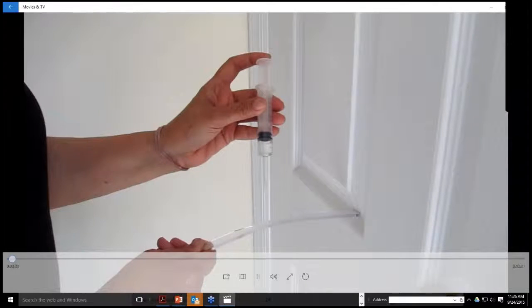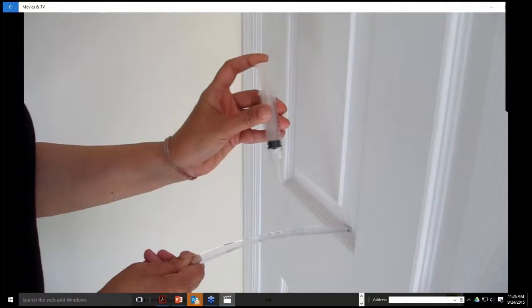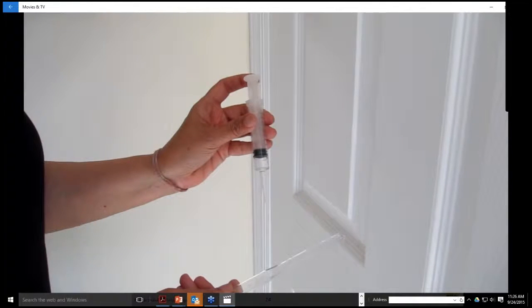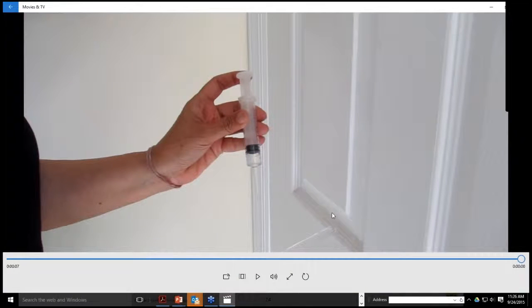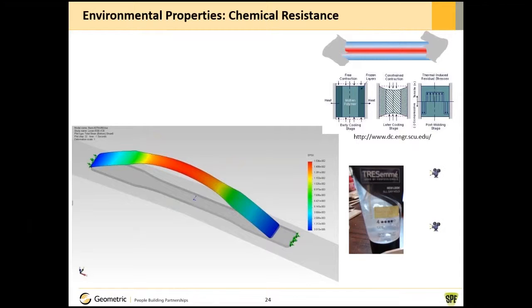and you put a drop of solvent on it, as my wife is doing here, and you have a catastrophic failure. You can see the bar completely broke in the middle and left this really rugged edge. So a plastic part which was fine, unbent, with the slightest amount of bending is now very, very sensitive to solvent. And it doesn't have to be harsh solvents like acetone. Even something that you put on your hair, the TRESemmé hair gel, if you have a headphone made out of polycarbonate and you're bending it in the process of putting it on your ears, even the TRESemmé gel will act on it and crack the headphone bar that's connecting the two sides of the headphone.